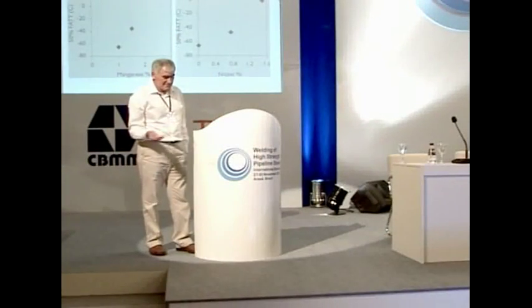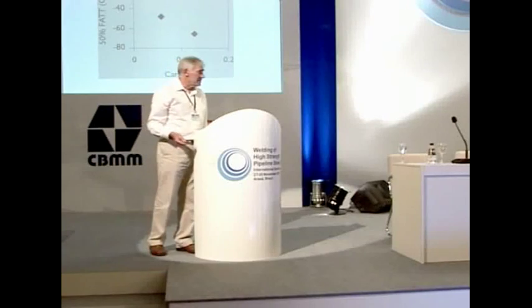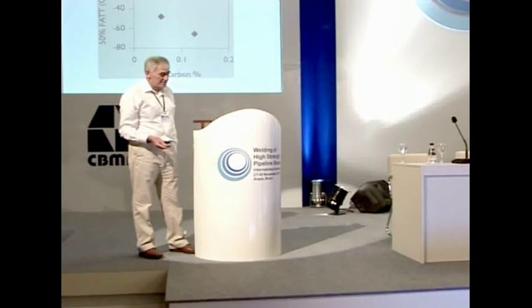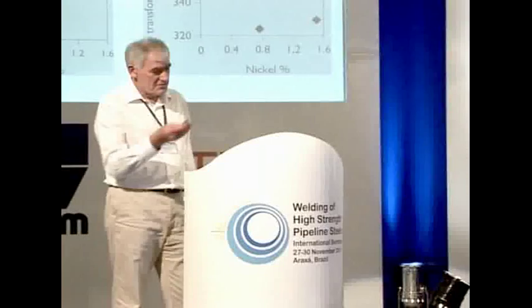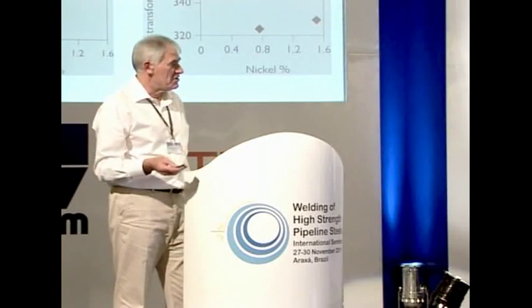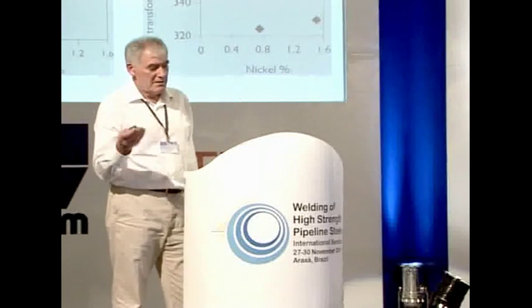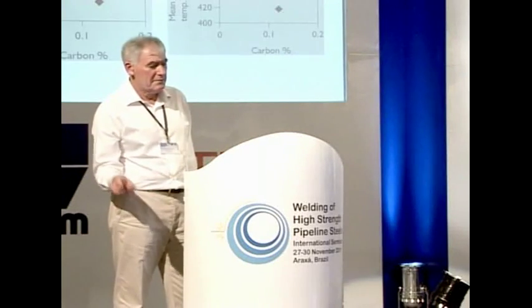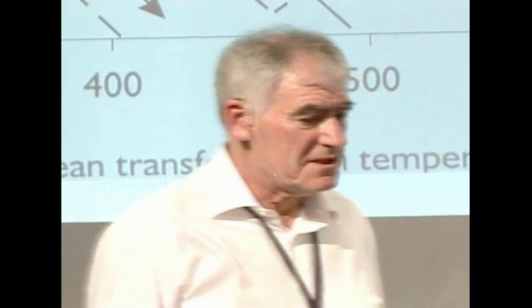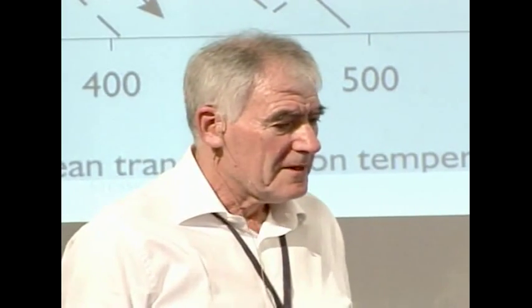Dr. Kirkwood effectively demonstrated that, taken out of context, individual sets of results could readily be used to demonstrate that any of the common primary alloying elements, such as manganese or nickel, could just as easily be shown to be detrimental to heat-affected zone toughness. More importantly, he reiterated his previously published belief that the optimum use of niobium will always occur when its incorporation into a steel composition is an integral part of a carefully tailored approach to specification, taking due account of the welding processes which will be encountered in the practical fabrication and joining of lengths of pipe.